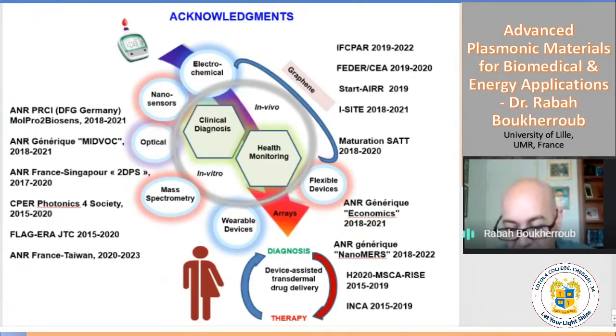However, you can also have hydrophobic or hydrogen bonding interactions, because on graphene, even when it's reduced, and I'm not talking about pristine graphene or CVD graphene, I'm talking about this chemically derived graphene, what you call reduced graphene oxide, you always have oxygen containing groups. And indeed, you can have hydrogen bonding. But definitely what dominates the adsorption of a molecule from the solution onto the graphene surface is the pi-pi stacking interaction. It's the aromatic interaction. So if you have any aromatic molecules, amino acids or polyaromatics, it will stack very quickly and very strongly. You cannot even get it out. That's exactly why people use pyrene-type molecules to functionalize graphene, because they form very strong interactions with the graphene layer.